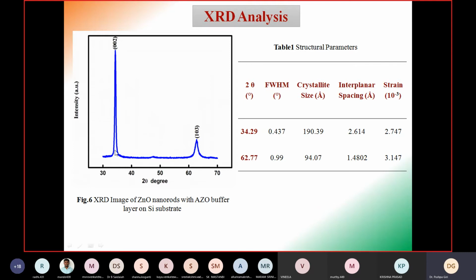Single crystalline structure can be seen, like 002 at 34.29. So if it is coming at this point, the graph is coming like this, that means it is single crystalline. The device is showing single crystalline nature, which means it is oriented toward a single direction. So the structure is very good if it is showing like this, the crystallite size is also bigger, the interplanar spacing, that means the distance between the two planes, is good, and the strain is also very low. So the X-ray diffractometer analysis gives the crystalline nature, or the structural parameters, of your sample.